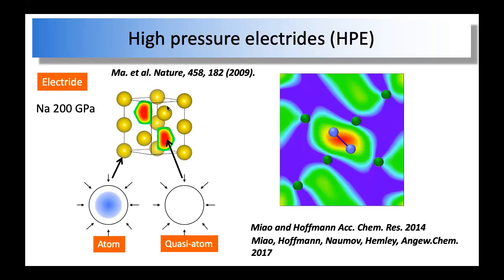It has long been noticed as a phenomenon that many metals under high enough pressure may become insulating or semiconducting, with a small gap. A very famous example is sodium under 200 GPa, which was predicted first by theory, and then confirmed by the experiments published in the same paper by Yanming's group. So sodium under 200 GPa suddenly becomes an insulator with a gap.